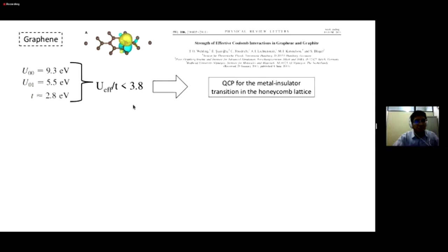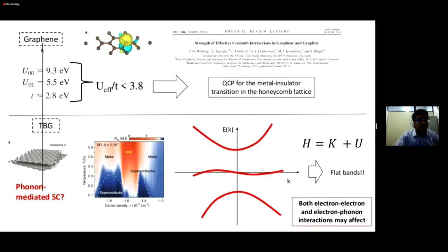over the hopping is below 3.8, and this 3.8 is what we know in the literature for the critical point for the honeycomb lattice, which means that graphene is not an antiferromagnetic insulator, because the interaction is not too big. Obviously, if the interaction is big, it can be an insulator, or it can be superconducting, I don't know. And this is what we see, for instance,